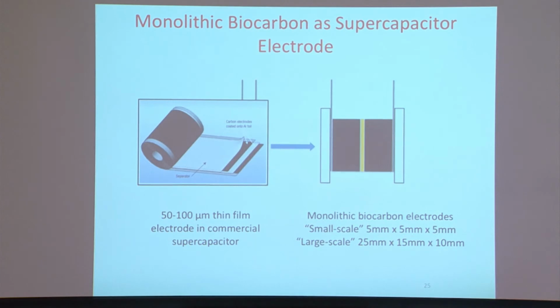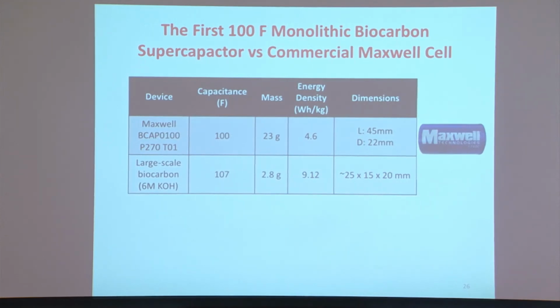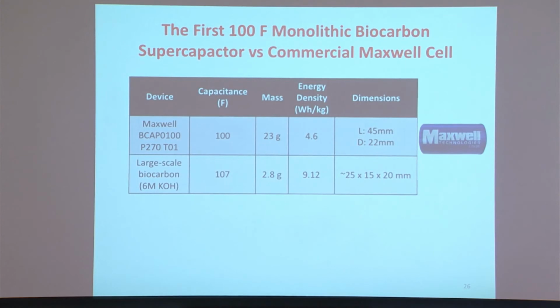So in this case, we tested the idea of using thick electrodes to replace those thin films, as thick as 10 millimeters. Usually the commercial one is about 50 microns. Our test was quite successful. This is a comparison with a commercial cell. Both are 100 farad. If you look at mass, the commercial cell is about 23 grams with an energy density of 4.6, and our cell with both electrodes is 2.8 grams, the energy density is higher, and the dimension is slightly smaller as well.